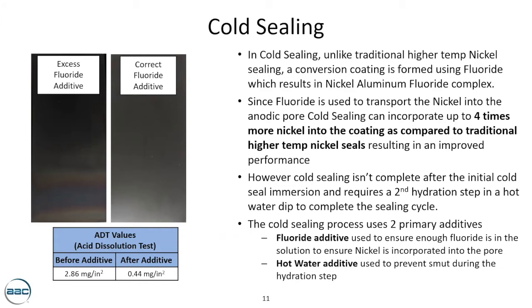If you put too much fluoride in there, you'll get an over-sealing phenomenon and you'll see iridescence. That's what the image on the left shows: iridescence associated with excess fluoride or an immersion time that's too long, 20, 30 minutes. Because remember, with the cold seal, you don't need to seal for longer than 7 minutes at most in certain cases. Depending on the application, maybe you go up to 10 or 15, but you don't need long immersion times like you do with the hot nickel and the mid-temp nickel.